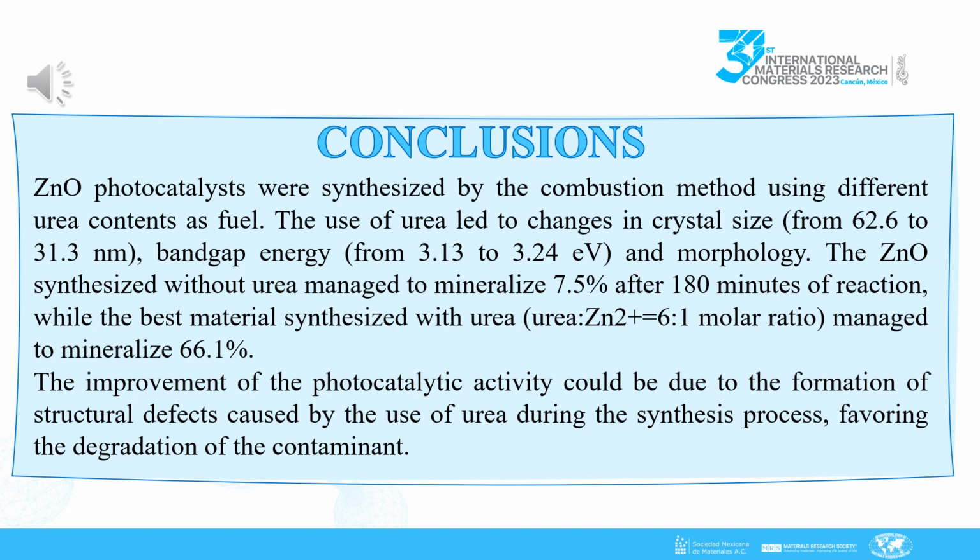The zinc oxide photocatalysts were synthesized by the combustion method using different urea contents. The use of urea led to a change in crystal size from 62.6 to 31.3 nanometers, band gap energy from 3.13 to 3.24 electron volts, and morphology.